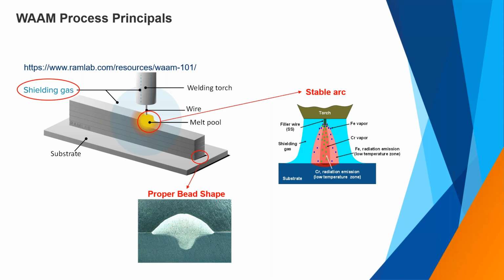So three aspects of this process have quite a significant impact on the results. One is the shielding gas which is used, and the other is the stability of the arc, and also the shape of each bead that you can see on the bottom, which is the cross section of each layer in this process. Now, these three aspects have been investigated for multi-material when we are depositing two different materials next to